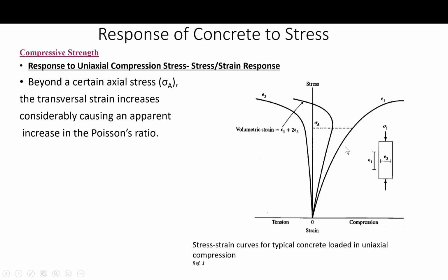So this is at the onset of the mortar microcracking. The gross volume of the concrete in compression also begins to increase. These effects are due to the great increase in cracking that is taking place.